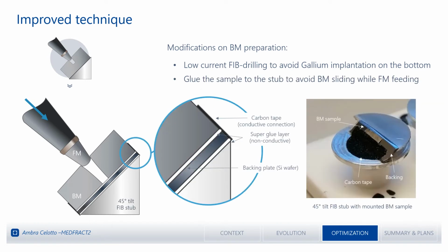Moreover, another improvement that was done to limit the sliding effect of the base metal while pushing the needle was to change the carbon tape that was originally sticking the base metal to the FIB stub with a super glue layer, which of course, being not conductive, had to be connected with the ground by a carbon tape connection to make it feasible inside the SEM, of course.